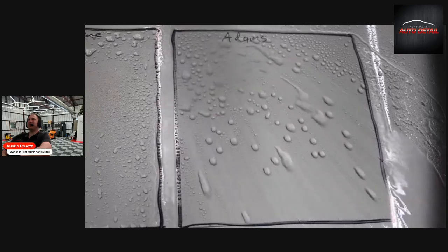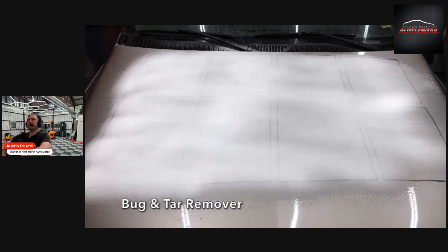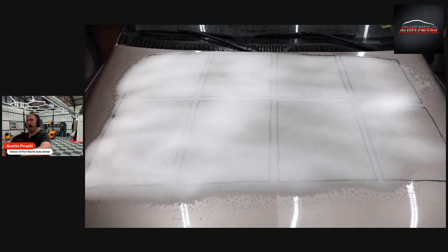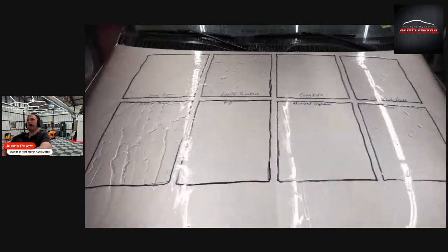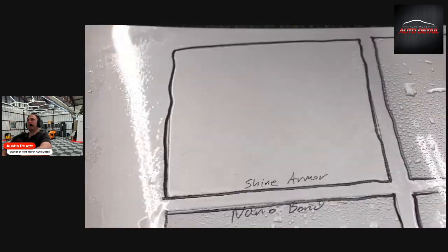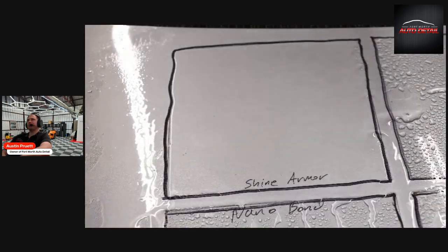Very impressive. Bug and tar remover is another powerful product that'll really put these coatings to the test. I'll give the bug and tar remover 3 minutes to go to work. After a quick rinse with water, I'll wash off the front hood with strip wash once again. And the Shine Armor is completely used up, and there doesn't seem to be any protection left.